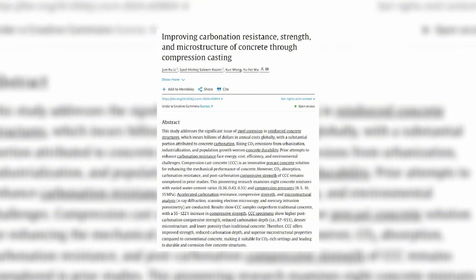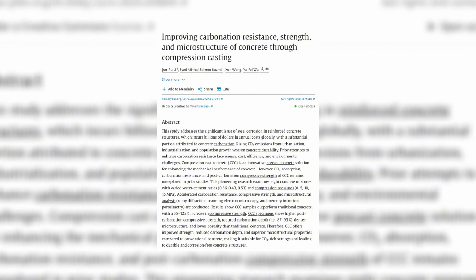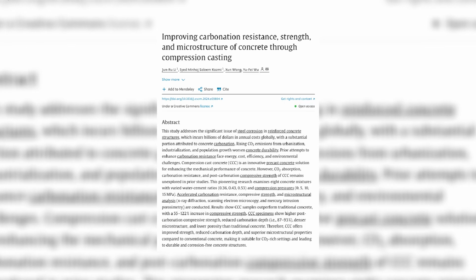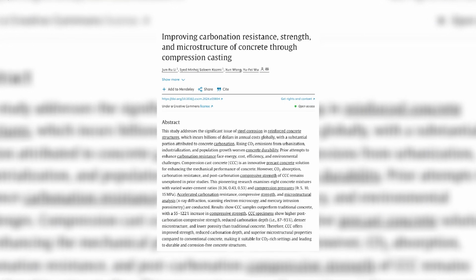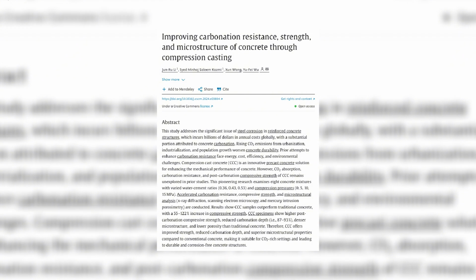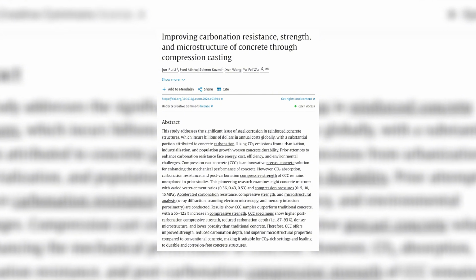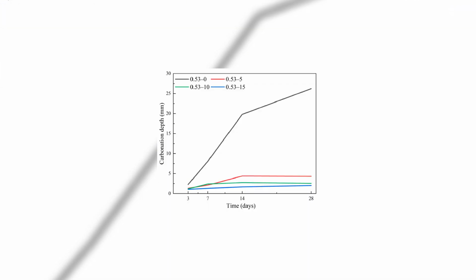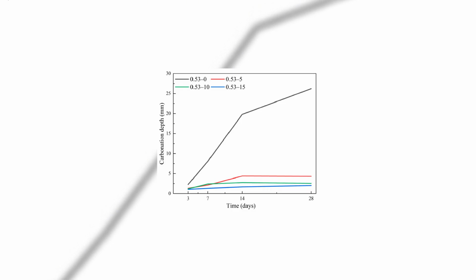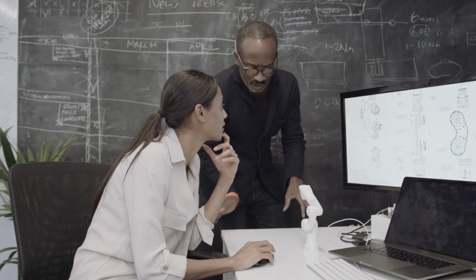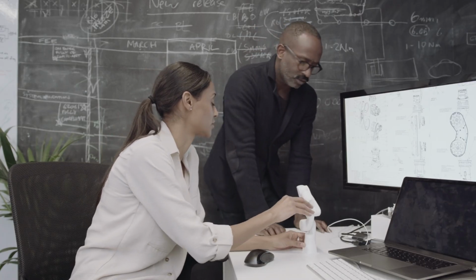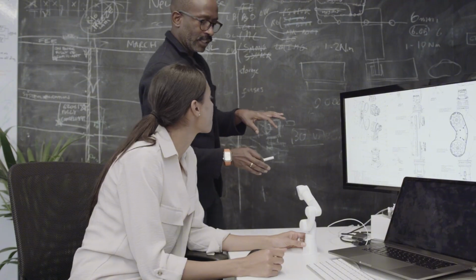A 2024 study examining compression cast concrete under pressures of 5, 10, and 15 megapascals reported compressive strength increases ranging from approximately 53 to 122%, depending on the mixture. The same study found that increasing the casting pressure substantially reduced porosity and made it much more difficult for carbon dioxide to penetrate the concrete. Other studies have reported better resistance to water absorption, freeze-thaw damage, and chemical attack. The explanation is not mysterious. Fewer large pores mean fewer pathways for water and corrosive chemicals.